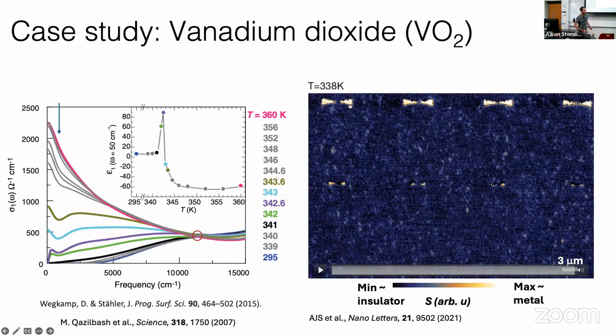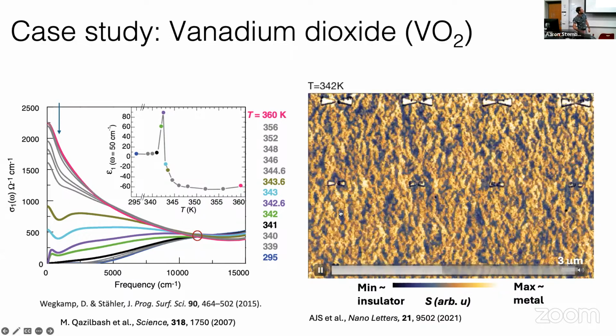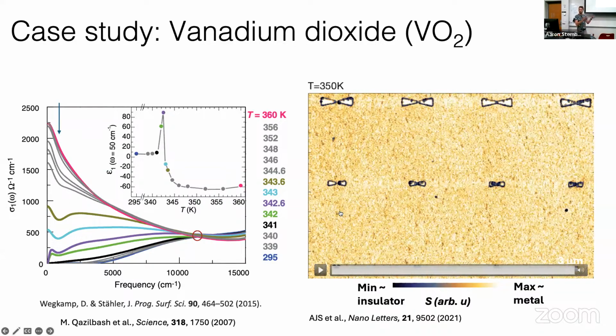And this gold bar has a scattering amplitude which is large, characteristic of a metal. And we compare the scattering amplitude on the film of interest. A low scattering amplitude is characteristic of an insulator, and a high scattering amplitude is characteristic of a metal. As we increase the temperature, what you can see is that the scattering amplitude, and thus conductivity, increases to a value that is close to what we observe on gold.